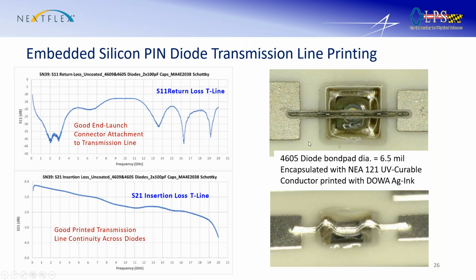So we've done some higher conductivity inks. We're working on tapering this line, because right now it's just printed straight across. But one of the advantages of the aerosol jet, you can actually taper this line and make more of a controlled impedance transition. So in our newer samples, we've pushed this cliff out, past the 20 gigahertz. So we're really pleased, and it's actually ready for technology insertion.